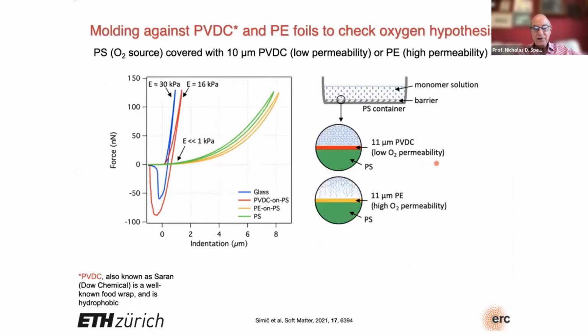The killer argument was really when we used PVDC, probably better known to you as Saran wrap, which is a very low oxygen permeability polymer from Dow Chemical. It's hydrophobic like most polymers. However, it behaves just like glass as a molding material. So that really confirmed this idea that it was the oxygen that was causing this mold effect. If we have polyethylene sitting on a polystyrene surface, which we know is full of oxygen, then polyethylene allows the oxygen to diffuse through. The PVDC does not.